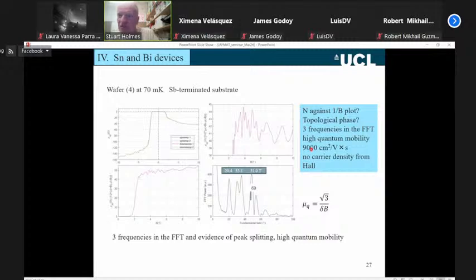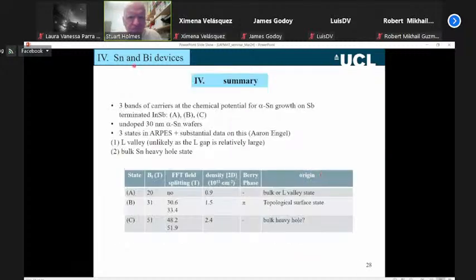As we've improved the material quality, the oscillatory structure coming from the surface state is much stronger, much more visible in the magnetoresistance. So just to summarize this, I've nearly finished my talk now. In tin, we see 3 bands of carriers. We'd like to be able to gate the structures so we can move the chemical potential in the region of interest where the bands are overlapping.